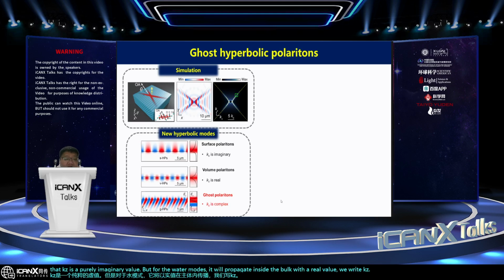Now we switch to the polariton in calcite. We can find this hyperbolic polariton is more like a surface wave confined at its interface, but it holds oblique wavefronts inside the bulk. According to the solution, we find this is mainly because of the complex Kz. We call it a ghost polariton, taking the name ghost from a theory work. We also think the ghost mode here comes from the hybridized mode of volume modes and surface modes.